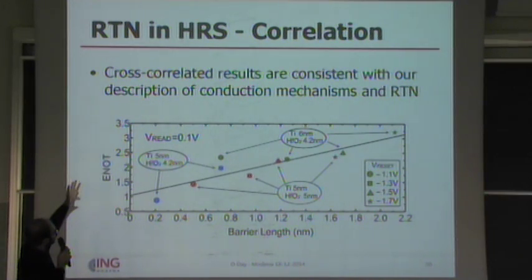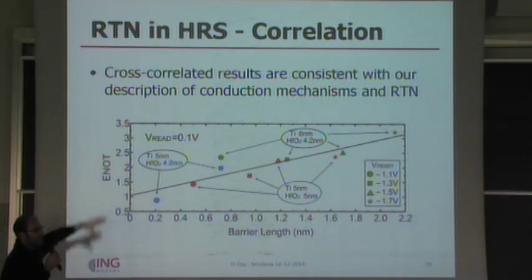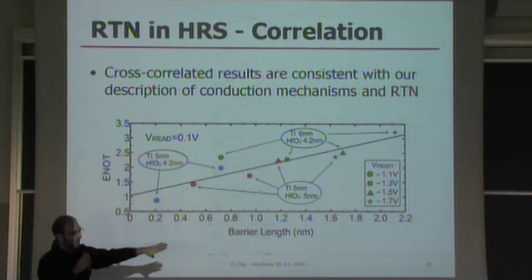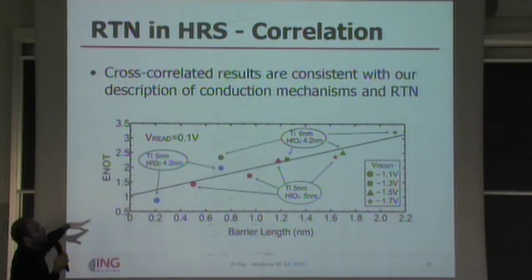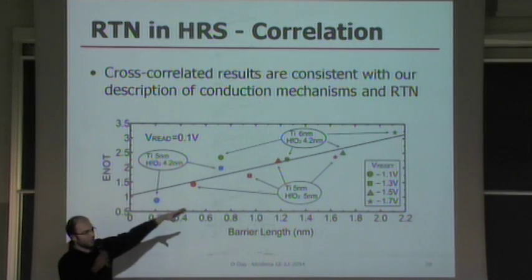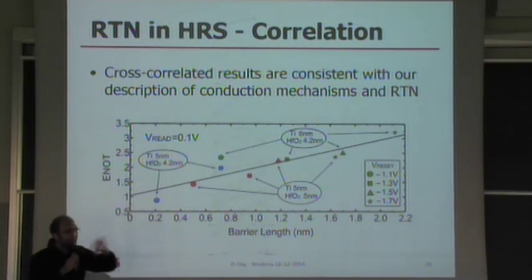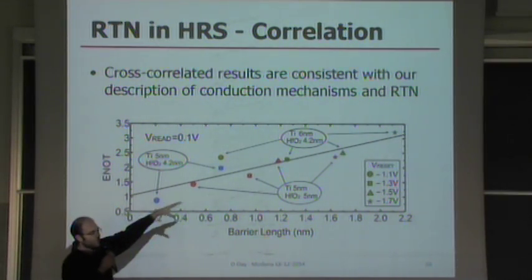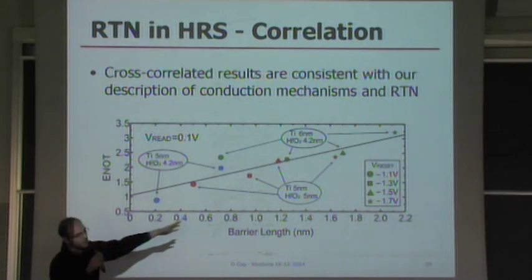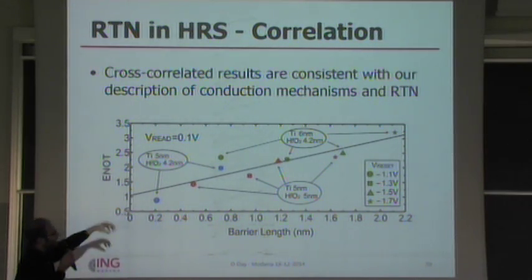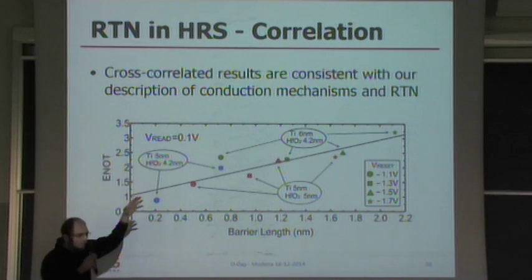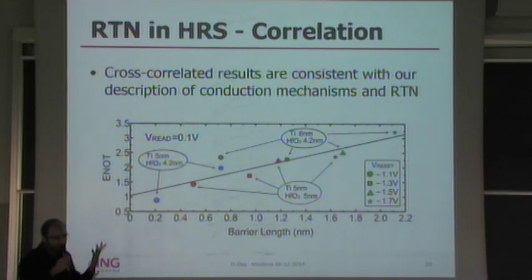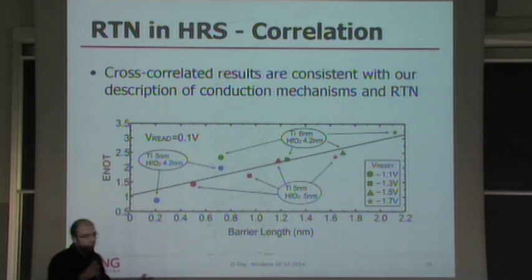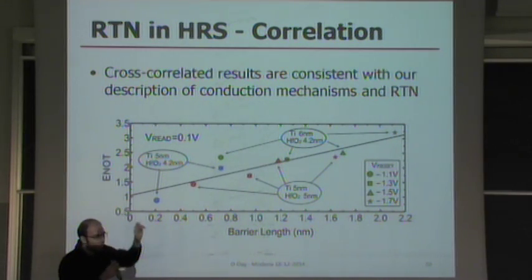If we look at this indicator, the effective number of traps, which is just a statistical indicator of the complexity of the noise, we see that there is a universal relation with the barrier thickness. So the thicker the barrier, no matter what the device structure is, no matter what the reset condition is, no matter what the current compliance is, it's just the barrier thickness. The thicker the barrier, the more the statistical probability that I have a larger number of defects, just because the barrier is thicker.